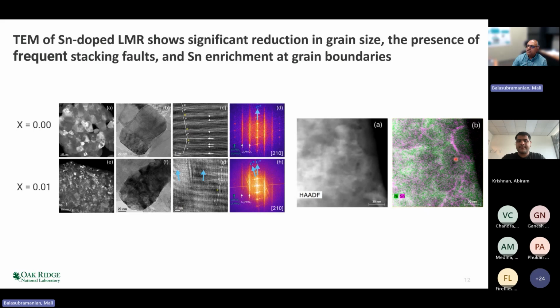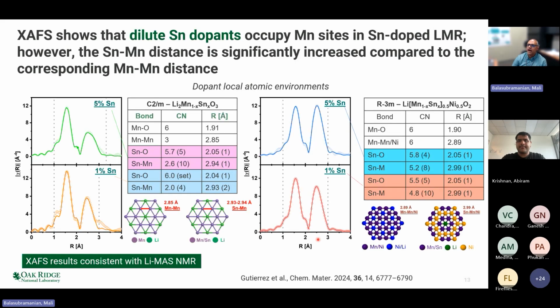And this tin goes to these boundary regions. Now, if you study these tin atoms by X-ray absorption spectroscopy, what you find is that you can clearly show that these dilute tin dopants occupy the manganese-type sites in tin-doped LMR.